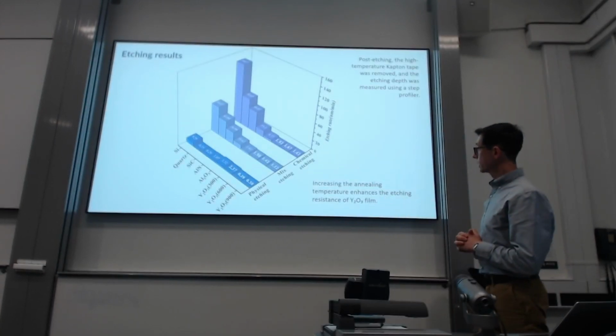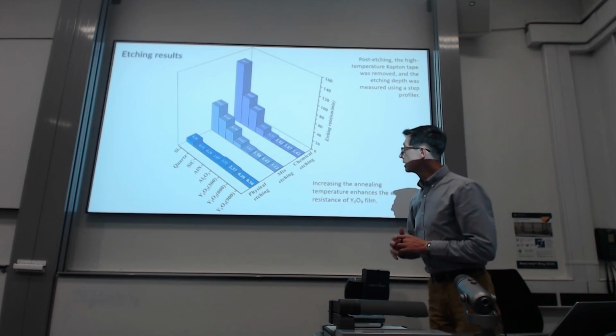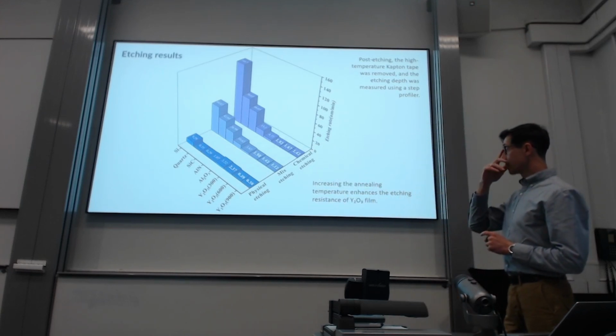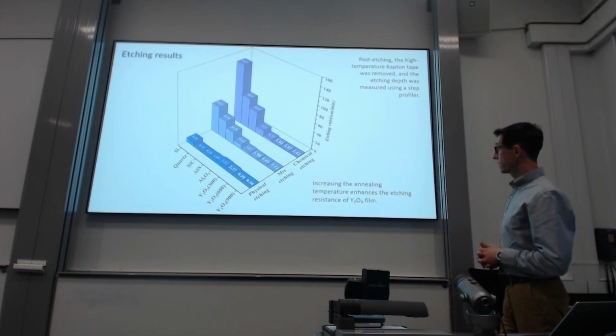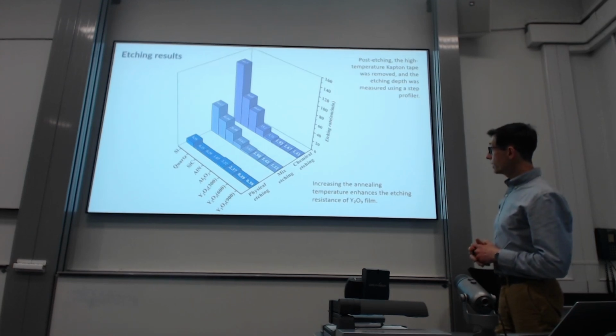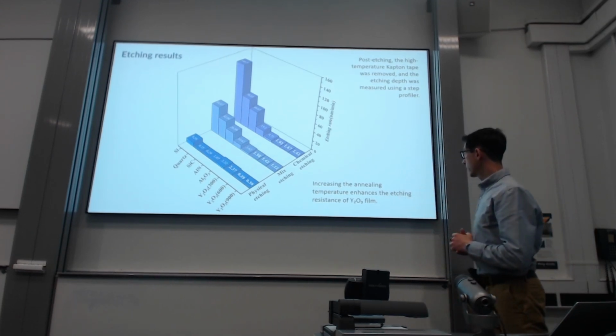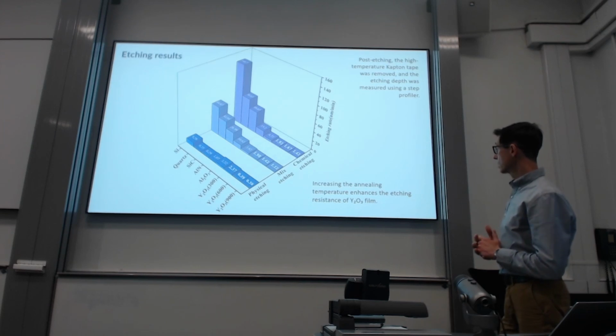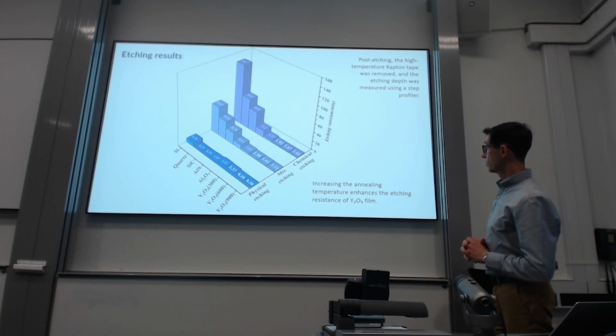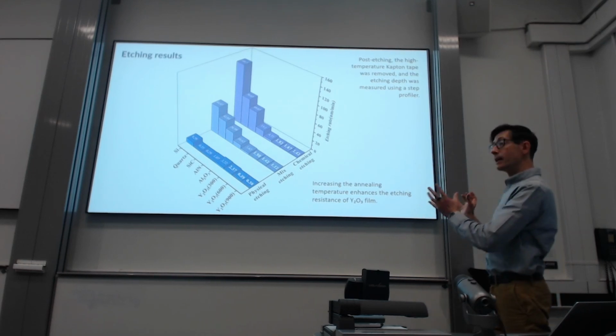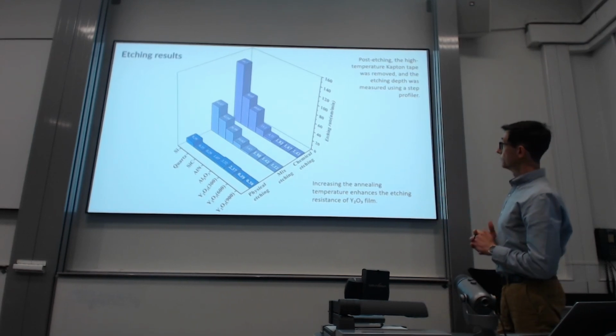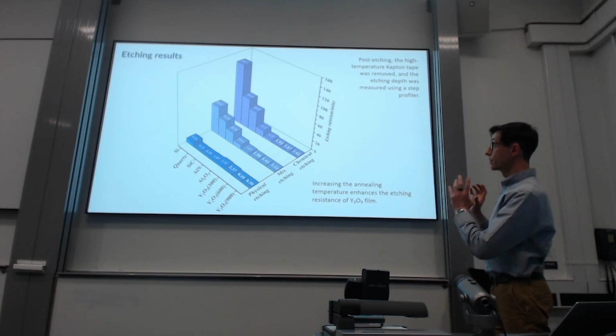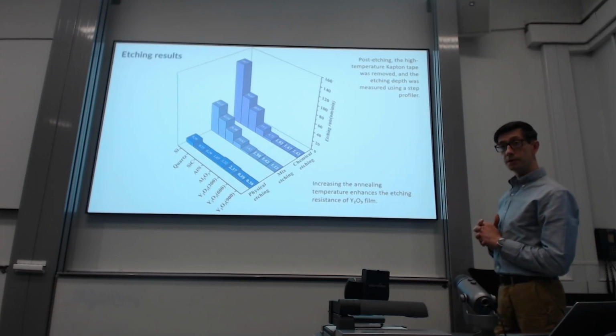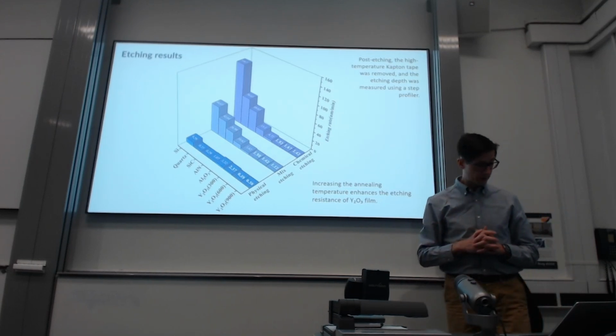three different cases of etching, and for comparison we also included some of the other materials typically used in semiconductor manufacturing process. So basically, broadly speaking, increasing the annealing temperature enhances the etching resistance of the yttrium oxide films. And that would be the main takeaway point from the first part, which is looking specifically at etching performance of those three coatings.